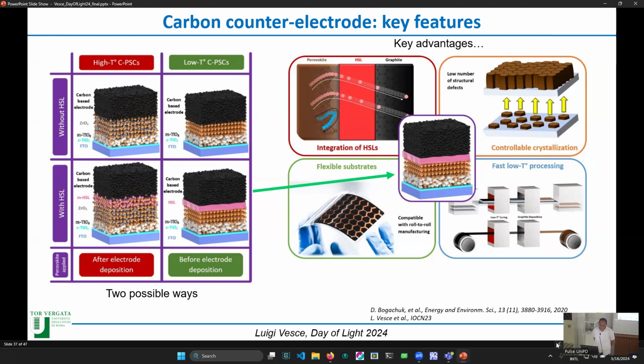And another concept is the low temperature carbon. In this concept, you can deposit the carbon after the perovskite. So you have not to infiltrate the perovskite, so you can also better control the crystallization of the perovskite. You can also integrate some HTL. This is compatible with flexible substrates and with the roll-to-roll process, so also to speed up the production line and so on. And so our efforts are mostly involved in the low temperature concept.